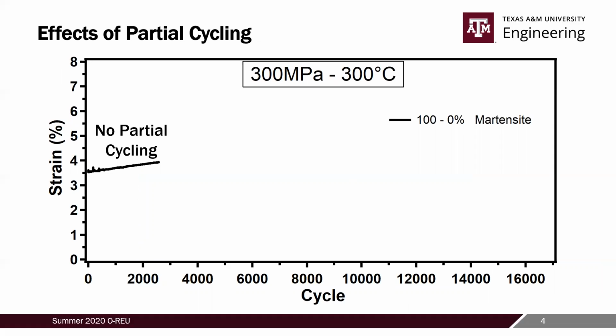For these actuators to be used in this particular application, they need to be able to be used up to 100,000 times, or 100,000 cycles. So with the current methods that we're using to cycle these materials, we're only able to achieve about 3,000 cycles, which is pretty far from that 100,000 cycle goal. So if we use another method of thermal cycling called partial cycling, we can dramatically increase this fatigue life.